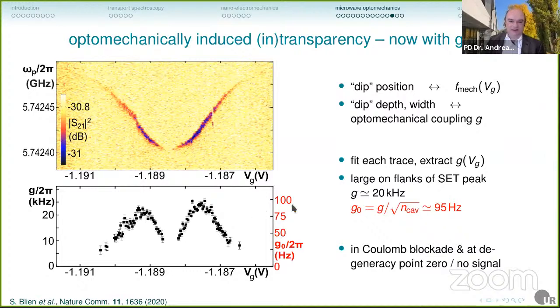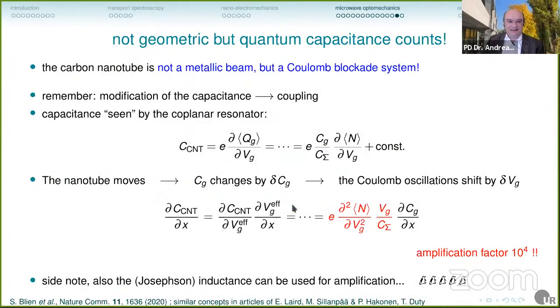What's happening? Well, the nanotube is not a metallic beam, but it's a Coulomb blockade system. And we've been going at this the wrong way. We've been looking at the geometric capacitance that changes when you move the nanotube. But in the end, what we need to look at is the quantum capacitance, the capacitance that is seen by the coplanar resonator. So how much the gate capacitance here, how much the gate charge here changes as a function of gate voltage. And then we also have to take into account that the nanotube moves. And that means not just that the geometric capacitance changes, but it also means that the Coulomb oscillations shift.